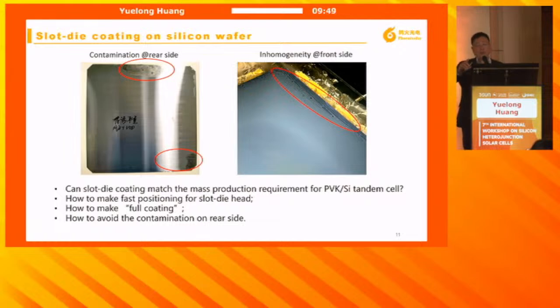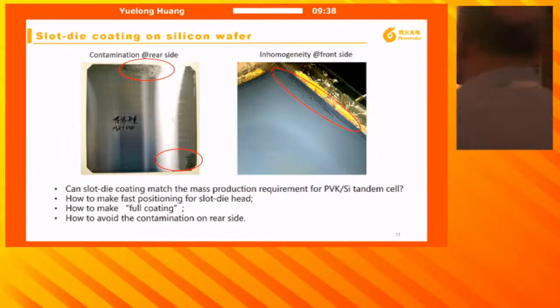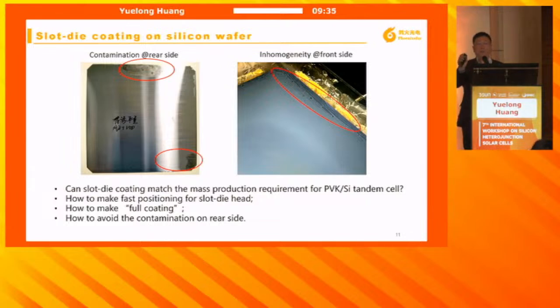So therefore, all the companies like Tongwei and others are looking for good equipment. They will ask, how can you minimize the edge of the coating, meaning the edge which is almost dead, with bad quality? Because if you make a single-junction module on glass, you will remove the edge side, for 1 centimeter or half a centimeter. But for silicon, it's not possible. You have to make a very good film for the whole wafer. So this is a problem.